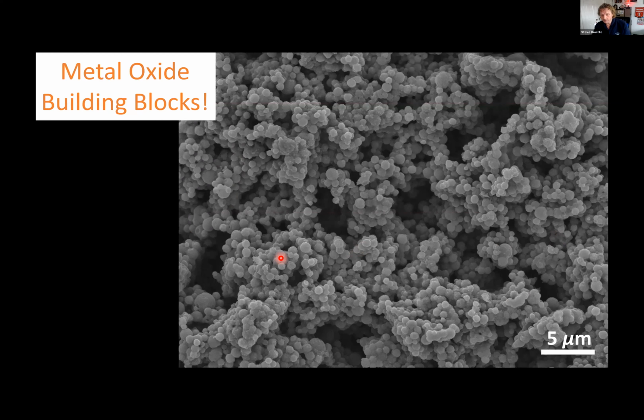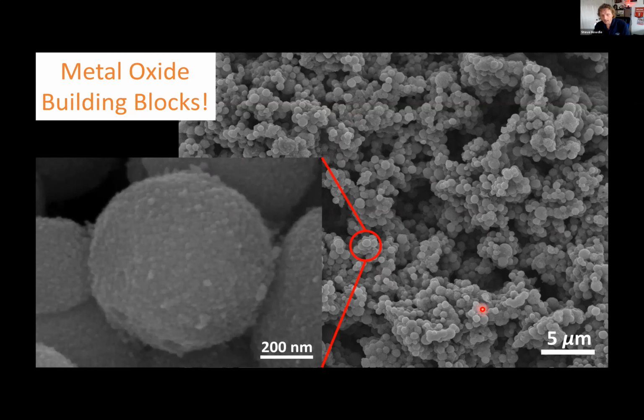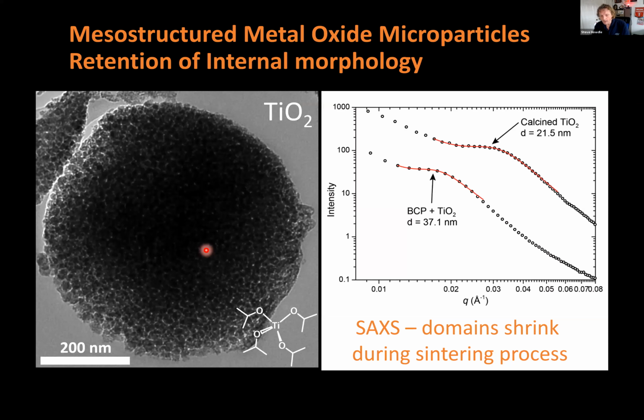Here you can see the SEM, and you can see that we've retained that spherical structure. These are still microparticles, and when we look in very closely, you can see the structure. If we started to actually cut one open, the cross-section shows us we still have the same kinds of structures present. The particles have shrunk in size a little bit because they're now no longer made of polymer, they're made of titania, but they have retained their structure.